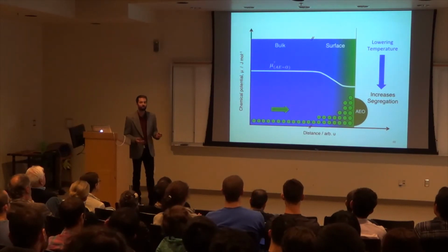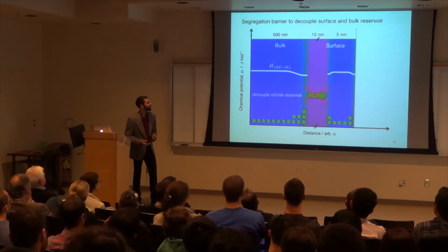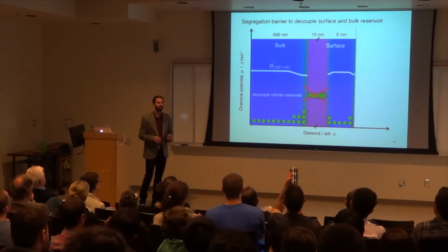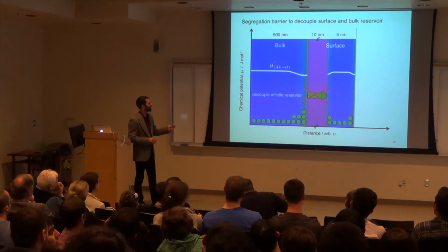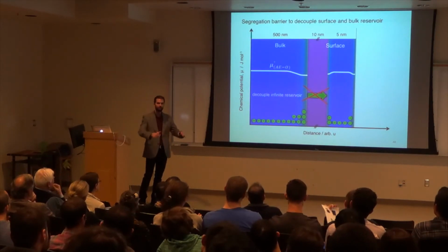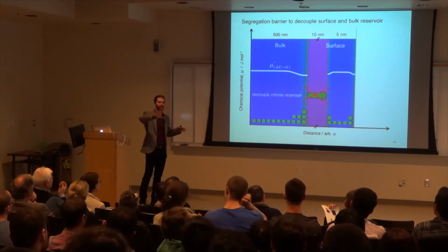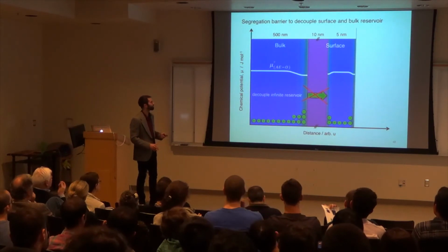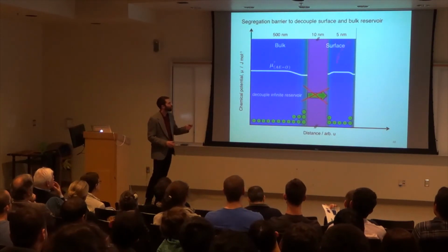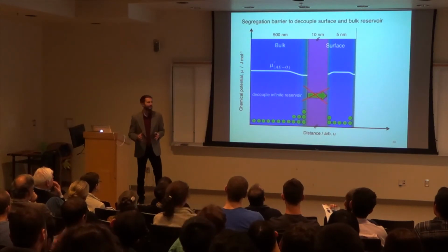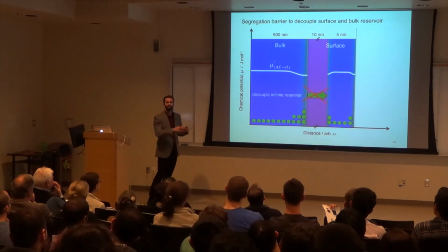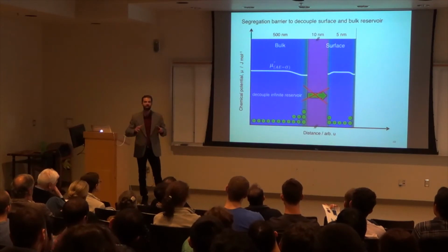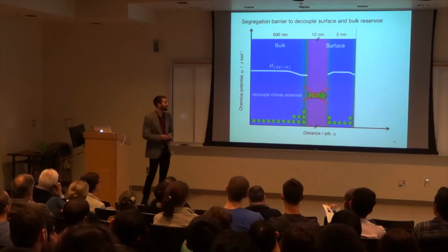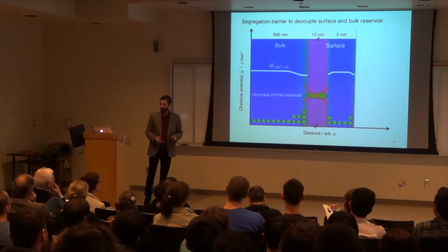So one thing that we've tried is essentially inserting a barrier just slightly below the surface. And what we've done here is we've decoupled the infinite reservoir from the bulk that allows the cations to move to the surface and to precipitate. Okay? And what you can imagine here is that when we have something that is so finite, like a 5 nanometer ultra-thin film, anything that segregates to the surface will destabilize the film and just really won't happen. Otherwise the material wouldn't stay in the state that it is already in. And this is what we observe.